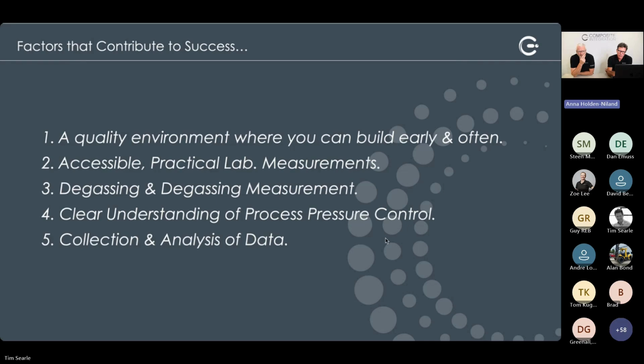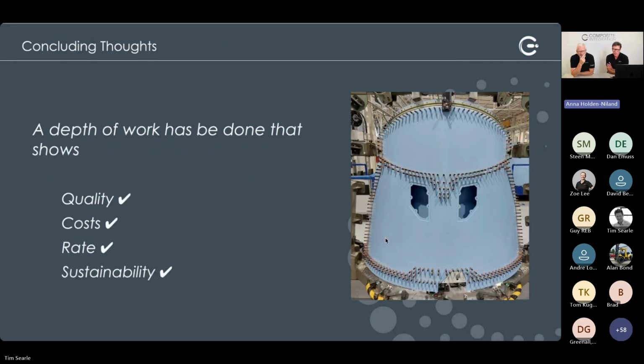But just by way of a closing slide, we've come back to this particular example. I think what we've aimed to do is to show the depth of work that we've done over a period of time. Just recapping on the thrust reverser door in the picture, made without an autoclave by resin infusion. The productivity was improved significantly, and the carbon footprint was reduced by about 60%, and it did show a weight saving over pre-preg. I think over several sectors with multiple complex and very often challenging infusions, competing with pre-preg on quality is now achievable.